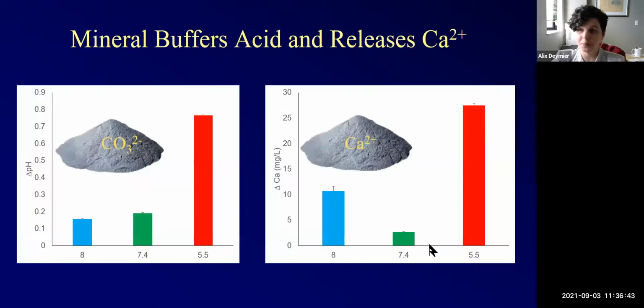So we see that when you just put crystals of carbonated apatite into solution, you do see a buffering ability. So the pH, if it started at 8, it actually goes up a little bit. 7.4 goes up a little bit. 5.5, it goes up a lot. So the same thing we saw with the ex vivo bone, we see here if we just put mineral into the solution. So probably releasing some sort of buffering moiety like carbonate.